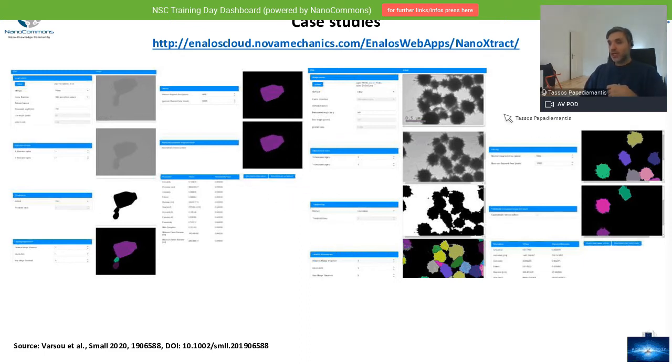But most importantly, when it comes to ceria nanoparticles that have been aged in phosphate, as is the case here, you can see this characteristic sea urchin shape that's been acquired, as captured by TEM, and is due to aging. In which case, you can use the tool, taking good care to play a lot with the parameters, and analyze the image and get some results out of it. Actually taking into account the sea urchin shape and so on, as you can see here, which will give you a better understanding of the roughness and the surface area of the material as it has been captured by TEM. So we will go through these